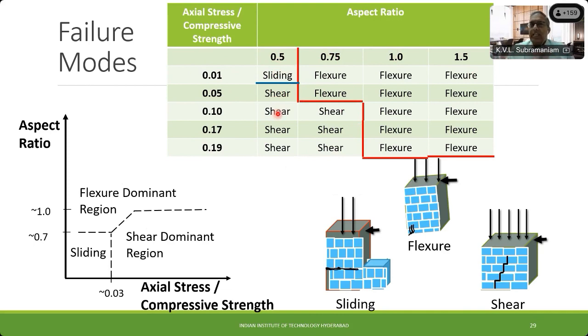Now, just to recap, if you remember, when I presented the photographs from the failures from the masonry, one of the buildings had diagonal cracking, and that happens in squat walls, aspect ratio 0.5 and 0.75 at moderate to high compression. 20% of the compressive strength of masonry is considered fairly high level of compression. But the minute we make the wall slender, the wall fails in flexure, which is basically produced by crushing of the brick.